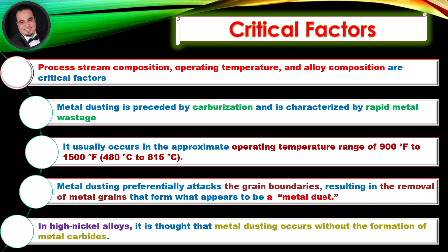Metal dusting preferentially attacks the grain boundaries, resulting in the removal of metal grains that form what appears to be a metal dust. In high nickel alloys, it is thought that metal dusting occurs without the formation of metal carbides.